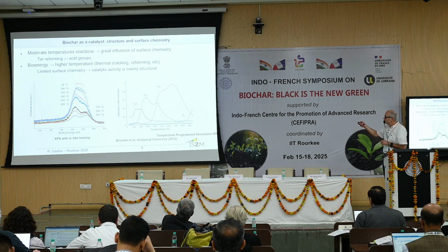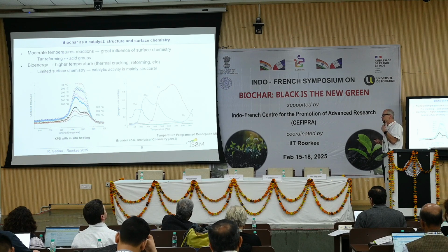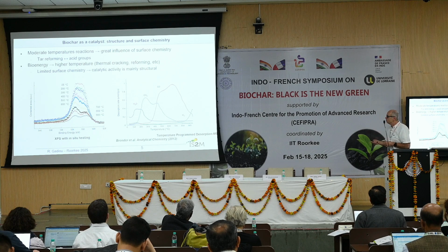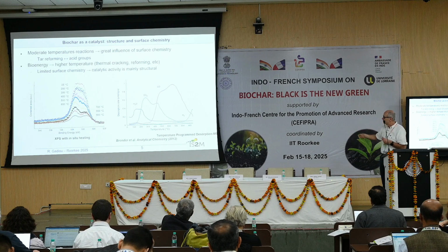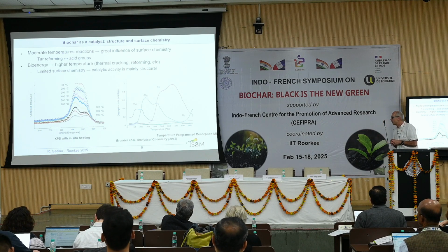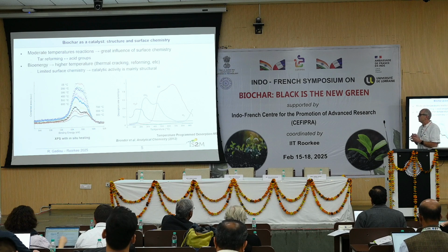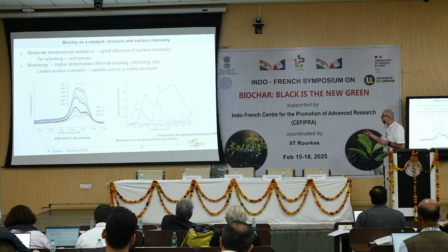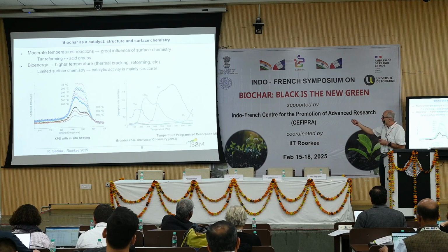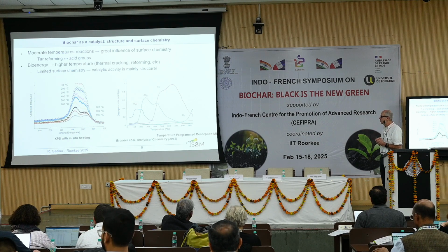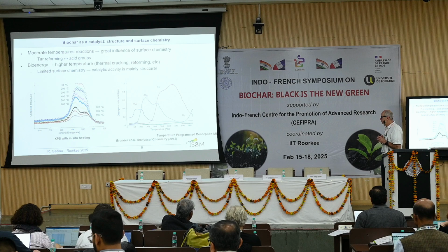And we see that we have a decrease of this peak up to 900 Celsius degrees. Not only a decrease, of course, which is known, but also a change of the shape related to the change of the surface chemistry. This can be compared with temperature programmed desorption with mass spectrometry analysis, which allows us to follow the functional groups which decompose as a function of temperature. So we can compare the two and see that we have, of course, the water which is evolving, related mainly to